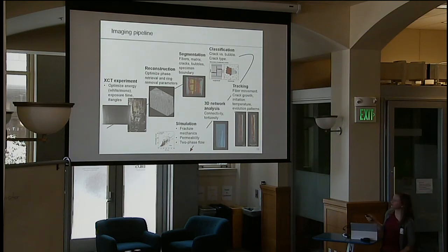The next step would be to track these cracks over time so that we can track their initiation temperature, and then track new cracks that form near the older cracks separately from the cracks that had formed before. And then finally, do a 3D network analysis with the ultimate goal of optimizing and understanding how fluid would flow through this crack network in the next stage of processing. And then finally, simulations so that we can predict and optimize this process, where we want to understand the fracture mechanics, be able to predict what type of crack network we're going to have, and then understand how fluid will flow through it, where bubbles will form, and what type of cracks we want to optimize for in later stages.